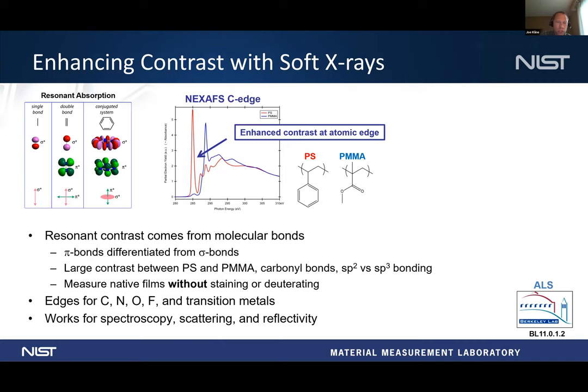And so red would be the polystyrene. And so the peak that you see there on the left is from the carbon-carbon double bonds that you have in the styrene ring. And the peak that you see in PMMA is coming from the carbon-oxygen double bonds. And then the other peaks that you have are just from some of the single bonds that you have in the material. But you can see there are pretty large differences in the absorption of those two materials. And so because of that, you can get very strong contrast from them in both scattering and reflectivity.